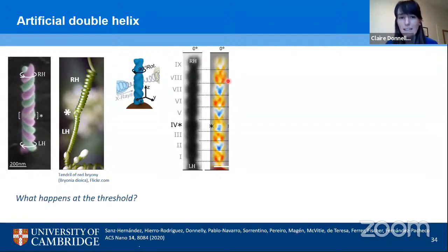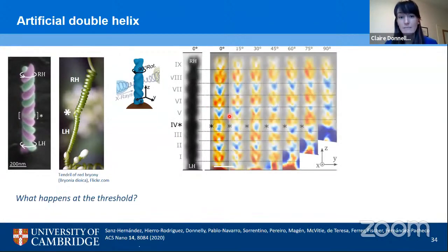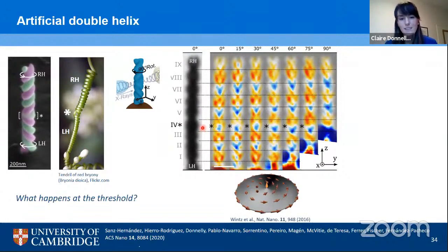So we first of all look at the 0 degrees image that we saw in the previous slide, and then rotate the sample at many different orientations. And we're looking specifically at this region of the image, which is indicated by these black stars, which indicates the position of our chirality threshold. Now, when we look at this contrast, it's actually reminiscent of a very well-known magnetic structure. That is the magnetic vortex. And this is for the following reason.